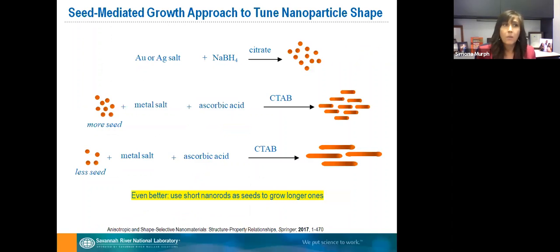Now, of course, for us spheres are great. They have this nice property that they are really dependent on the size. But a lot of times we are focused on different shape nanoparticles. So by using a slightly different procedure, and in this case you can see that we have a different surfactant, cetyltrimethylammonium bromide, we can generate these gold nanorods. And by using the same three-step approach, we can tune the size of these rods. So we can go for long rods, or we can go with shorter rods.